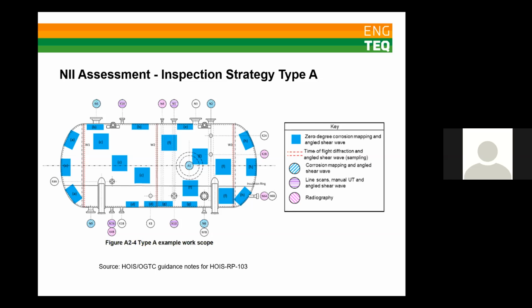So there is a much higher number of nozzles selected than the 5 to 10% for the shell. And in this case, the reason for this is that the main process nozzles are considered to be unique. They may see different process conditions to the rest of the vessel shell, so they should be considered individually very carefully. So some of the minor nozzles can be grouped together and be considered similar. So on the right hand side at the bottom, you might see nozzles N6A and N6B are clearly similar, and only one of those has been selected for inspection. There's no real value in inspecting both of those in this case.